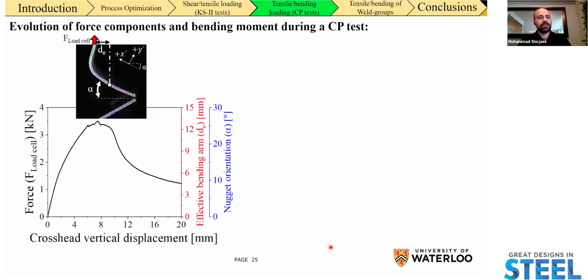Now let's look at the evolution of some of these parameters in an example of the CP test. This is an example of the short arm geometry, where the black line is the traditional load displacement curve, and the red line shows how the effective bending arm applied to the spot weld is changing. Initially we had around 10 millimeters of bending arm, and that number reduces to less than 3 millimeters by the end of the test.